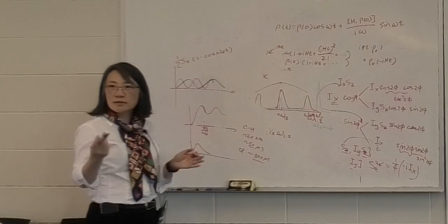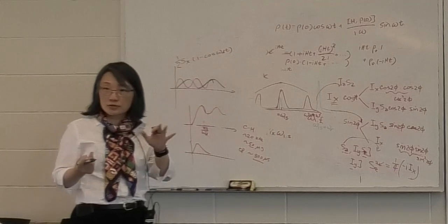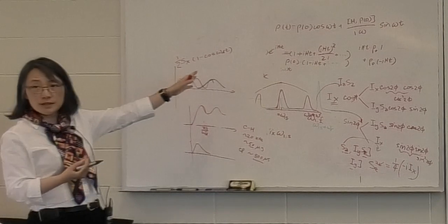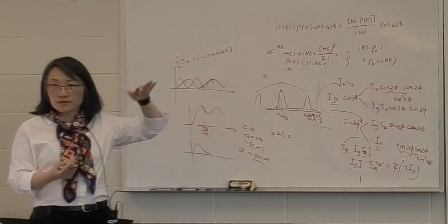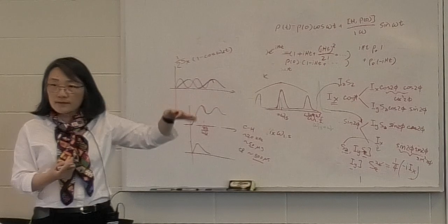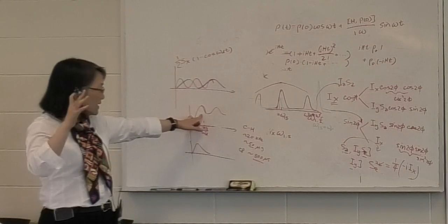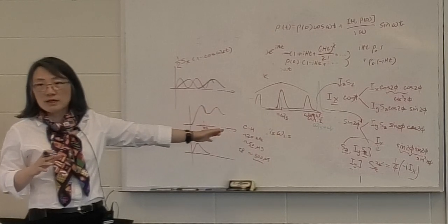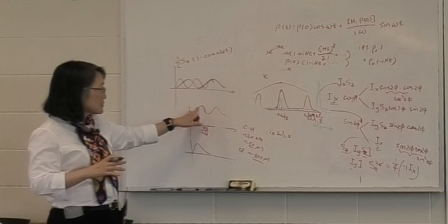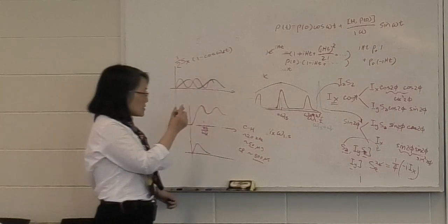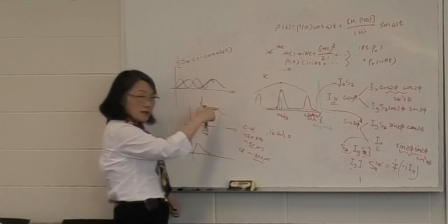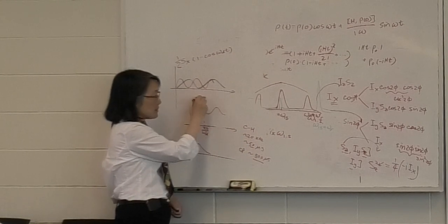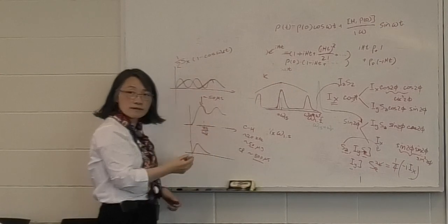And what is Lee-Goldburg CP? Lee-Goldburg CP is when I have killed the proton-proton homonuclear dipolar coupling. In regular CP, I told you that in the spin lock on the proton, there's still homonuclear proton coupling going on. And that's going to impact in some way. I have to think about exactly how it impacts, but you don't get clear oscillations usually for the regular CP. But under Lee-Goldburg proton homonuclear decoupled situation, you get nice patterns. So you can see this. Yes, it's possible to observe in the CP oscillation something that relates to the coupling strength. And I don't remember, but I think for CH bonds, something on the order of 50 microseconds is true.